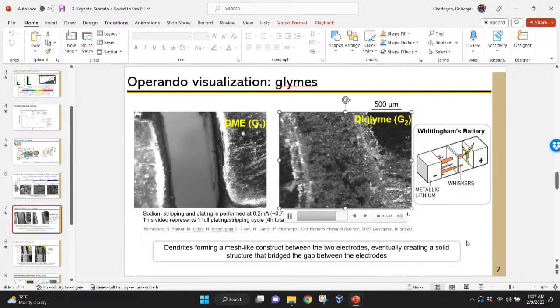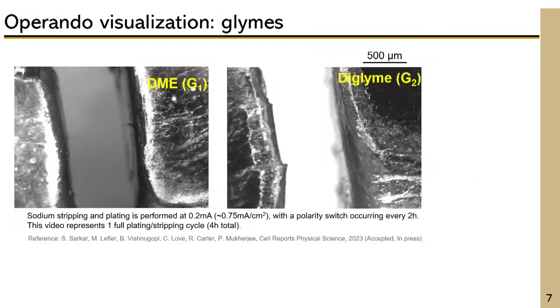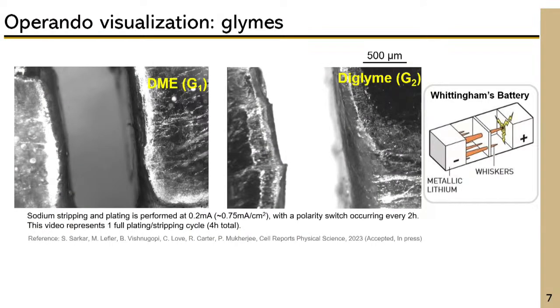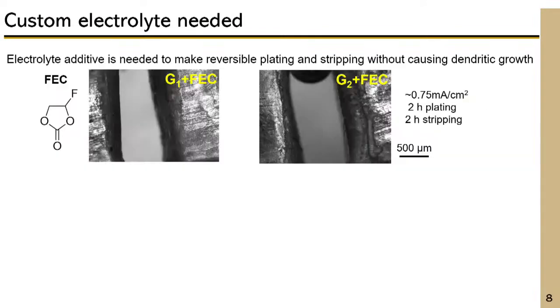So what's the next step? The next step would be to have a co-electrolyte additive and see if we can stop this kind of dendrite. For that reason, we added a co-electrolyte additive. That's a common approach: you add a very small amount of another electrolyte with an optimal property in the hope that it forms a stable interface. In this case, we selected fluoroethylene carbonate.